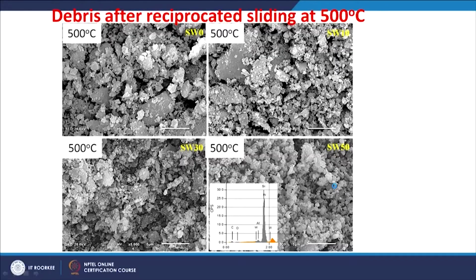The silicon carbide tungsten carbide composite surfaces after reciprocatory sliding at room temperature and high temperature of 500 Celsius show a difference in the mechanism. The fracture is increased when the testing was done at higher temperatures. At room temperature, as the tungsten carbide content is increased, we can see certain tribochemical layer formations and removal, whereas such tribochemical layer formations are not found in those composites worn at high temperatures. The debris also shows no presence of any cylindrical shaped debris. These are all fractured grains and no signatures of any tribochemistry.